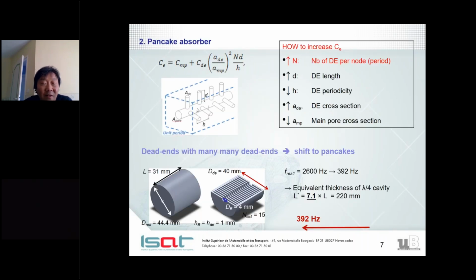So what do we want from this formula? We want to increase the compressibility, because if we increase compressibility, we will reduce sound speed, and then this will reduce the resonance frequency. And with this formula, there's not much we can do on the main pore compressibility, because it depends on the diameter of the main pore. Actually, this is one of the parameters that Camille presented, one of the Johnson-Champoux-Allard parameters. But we can play on the dead ends.